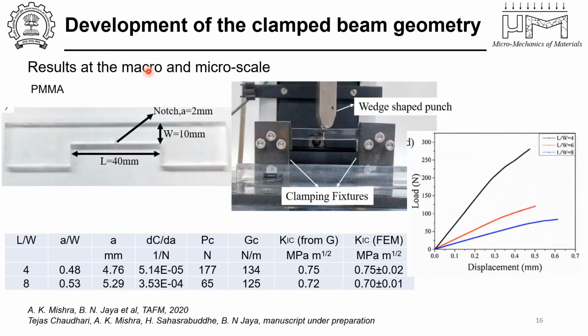Yeah, so some results that we come to. First, we tested on a known material like polymethyl methacrylate, which is a linear elastic brittle polymer, which is extensively used for these kinds of calibrations and validations. So this is a macro scale geometry. We loaded it in bending. And as you can see here, using critical loads, we were able to calculate both the fracture energy in terms of GC as well as K1C.